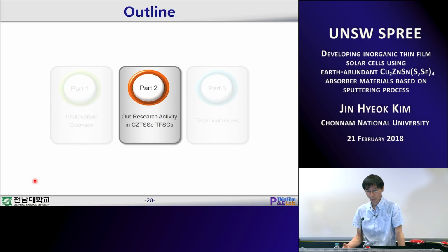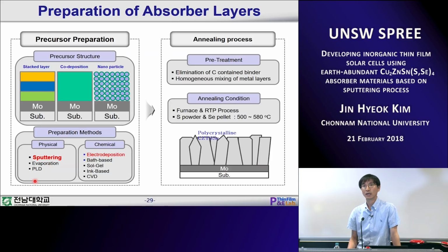Okay, now let's move on to the research activities in our group. There are many different ways to prepare absorber material. To make this kind of polycrystalline absorber layer, we have to prepare a precursor first. After preparing this precursor, we have to do an annealing process. We call this a two-step process: first, making the precursor, and second, crystallization. During this crystallization process, we add sulfur or selenium in the annealing atmosphere. So from this metallic precursor or sulfide-included precursor, we can make CZTS or CZTSSe polycrystalline absorber material.